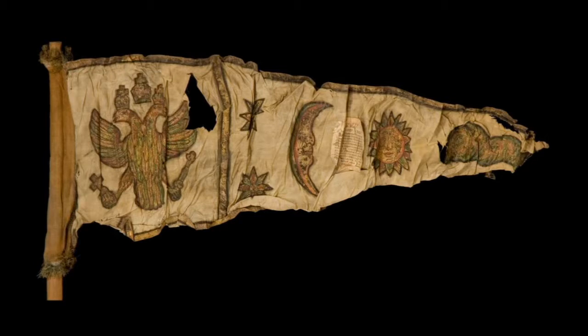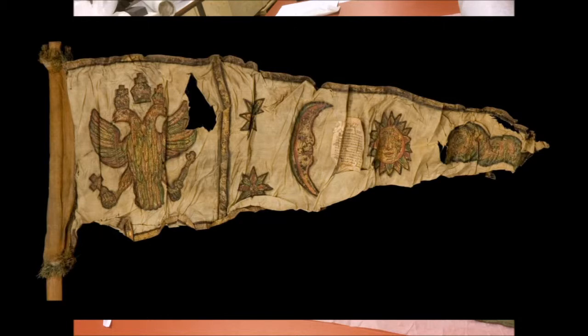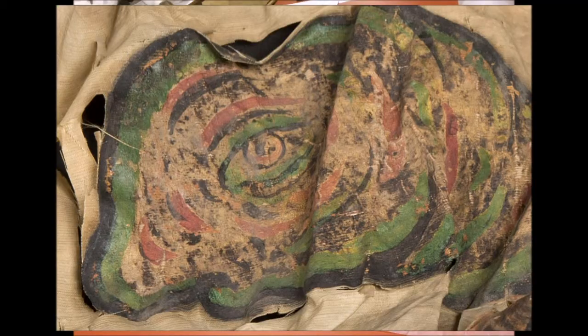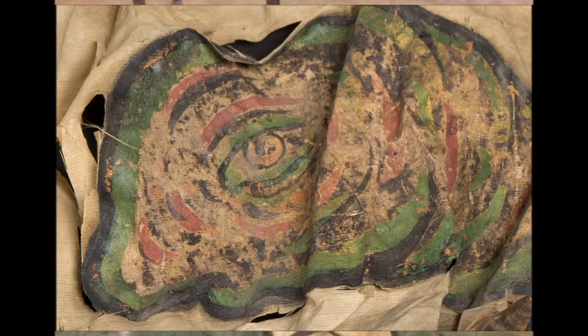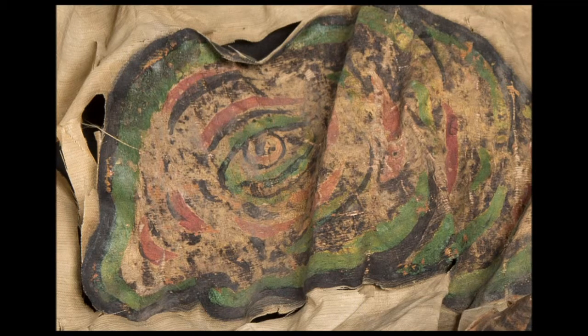They have become deformed after hanging for a long time in the Riddarholmen church, are very dirty and torn and show damage due to exposure to light, which is seen as diagonal rays across the cloth. Some of the material is quite stiff, so that at the border between painted and unpainted surfaces, the material is extra sensitive, resulting in ruptures.